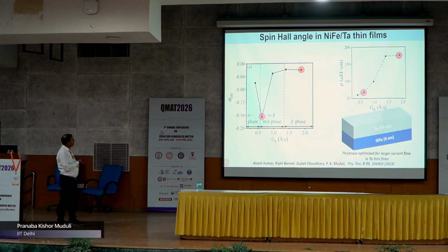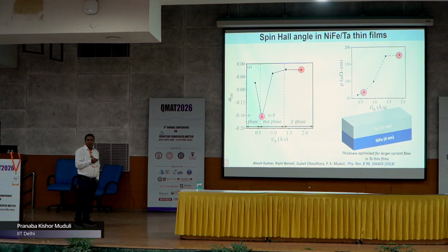One example that I would like to give from our group is that if you use tantalum instead of platinum, in the tantalum you can actually change the crystalline phase by changing the growth rate, and then you can see a much higher spin Hall angle, up to 16%, by using a mixed phase where you can see extrinsic spin Hall effect dominating over the intrinsic spin Hall effect, and that leads to a higher spin Hall angle.